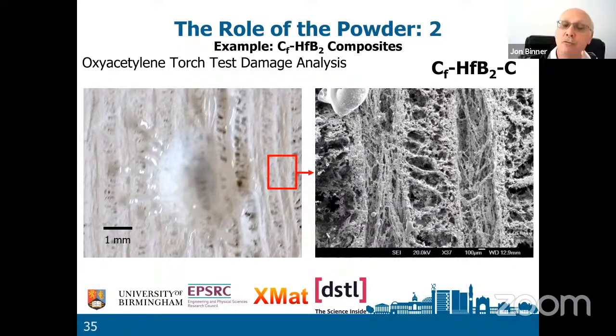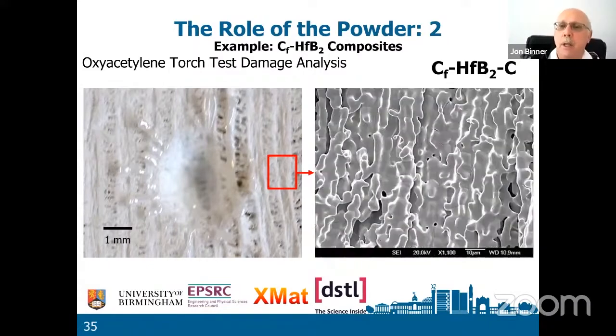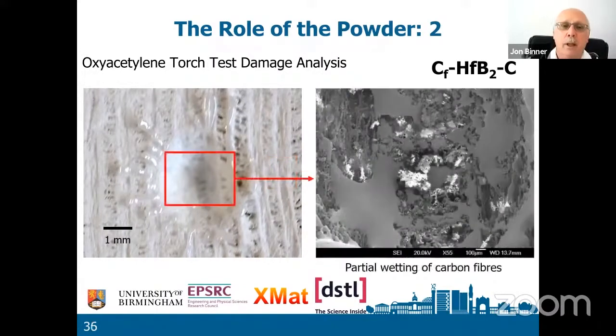So we're looking to the right of the hot point. And if we zoom in, we can see that the hafnia, which is formed as the hafnium diboride oxidizes, is sintered. And then if we look down the hole itself, you can see here some gray regions. They are actually formerly molten hafnia. So we know we're above the melting point of hafnia.